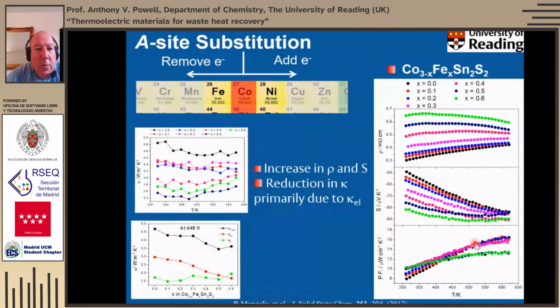So another way that we can tune those properties of adding and removing electrons is actually to focus on the A site cation, so that's the cobalt cation, and replace it with either iron, which removes some electrons, or nickel, which will add them. If we use nickel, we find that actually all that happens is that we add more and more electrons to that upper band, and the material becomes increasingly metallic, and the thermoelectric properties really fall off quite dramatically. Whereas if we do iron, we see a fairly limited range of solid solutions, so only up to about 0.6 ions, and we degrade the electrical properties, which is the resistivity and the Seebeck coefficient.